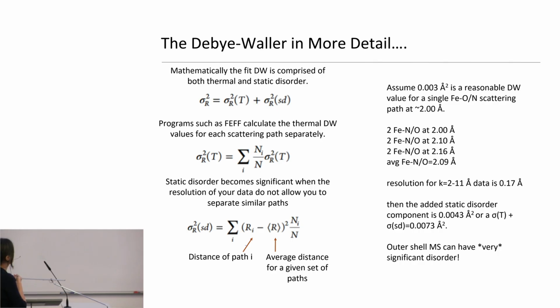And when we do that, we have the problem that we start to have a static disorder component that becomes significant. So as I already pointed out, this Debye-Waller has a thermal component, T, and a static disorder component, SD. And what actually happens then is as I have a distribution of distances, I need to know how far those distances are displaced from the mean. And so this is just an example where I have a range of iron distances and I don't have the resolution to separate all of them out because I have too short of a k range. Then I basically end up with all of them grouped at an average distance and with a large static disorder term. So the static disorder term I'm calculating here is around 0.0073.